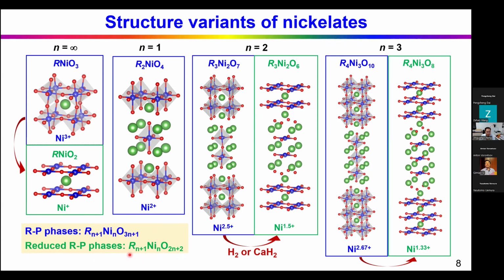These reduced RP phases can be obtained by reducing the corresponding RP phases, this blue one. Here you can see the coordination of nickel changes from octahedral to square planar coordination. These RP phases can be reduced by heating them in flowing hydrogen or with something like calcium hydride to remove the apical oxygen. Then you can get this reduced phase.